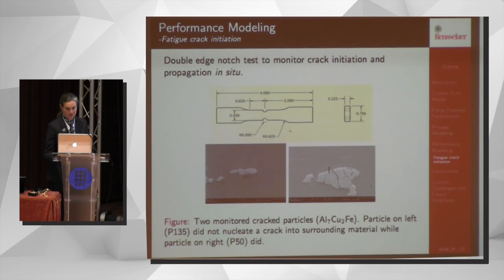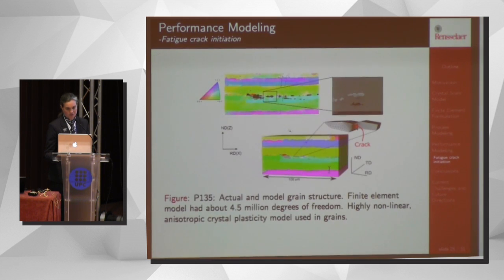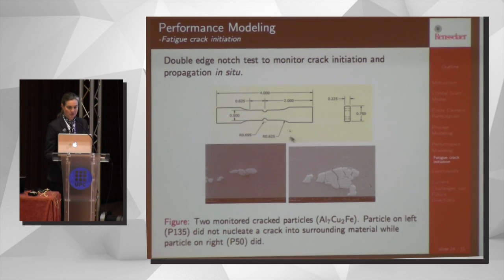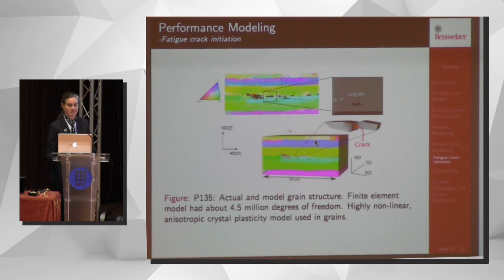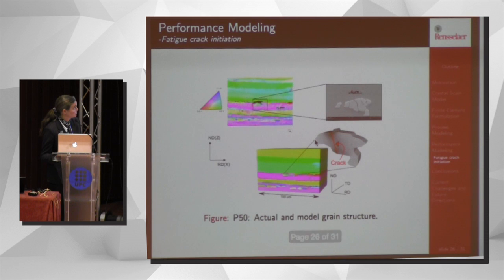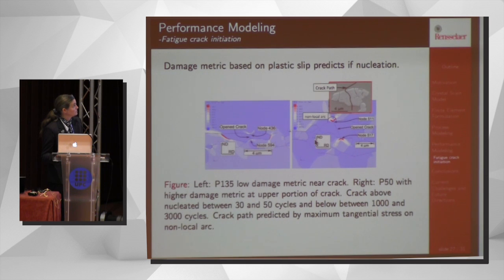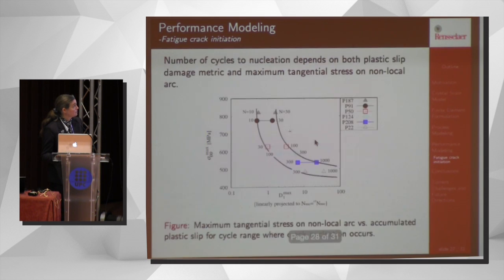This is aluminum alloy 7075 T651. And there was an experiment, a double-edged notch experiment, where they looked at second phase particles that tend to crack and lead to crack nucleation in the material, and they tracked a bunch of them, and some of them nucleated cracks and some did not. So we simulated these. This is one where the crack did not nucleate into the surrounding material. This is one that did. And we developed a damage metric that seemed to be very predictive of determining whether or not the crack nucleated into the surrounding material.